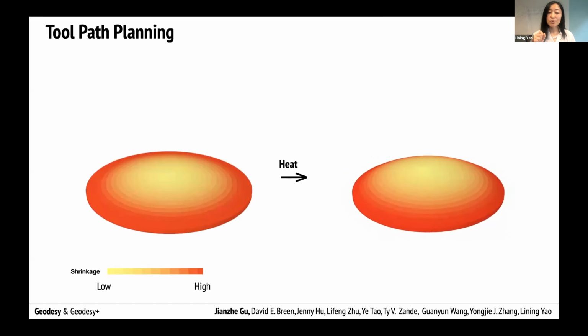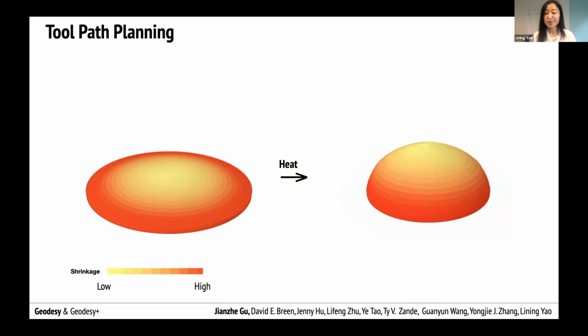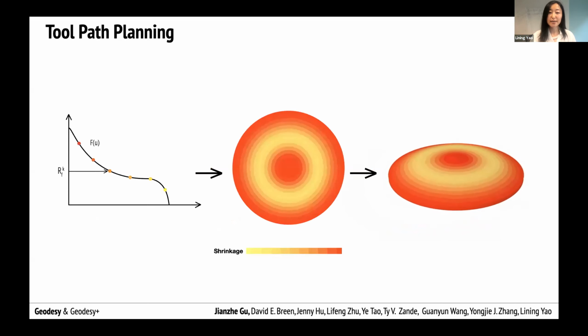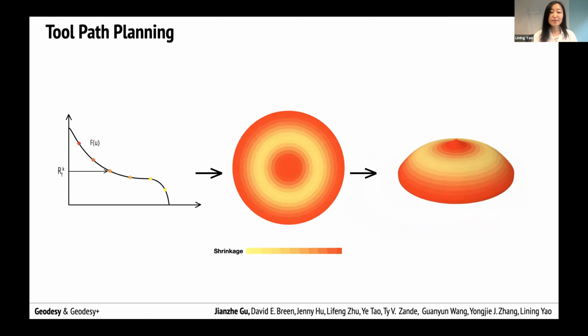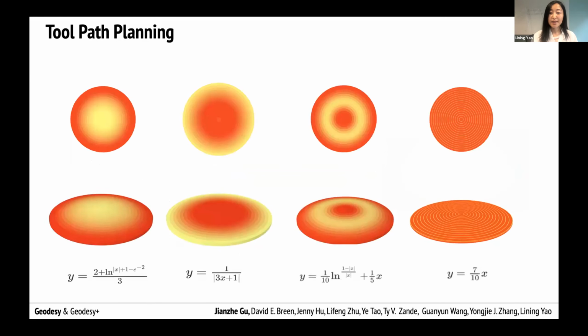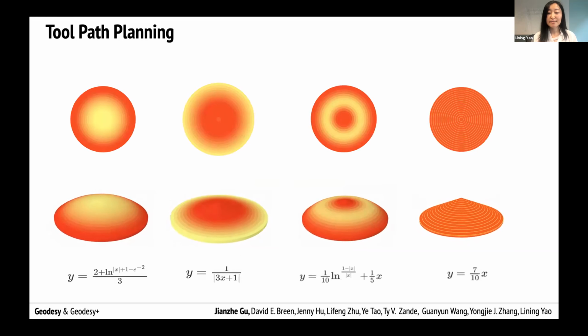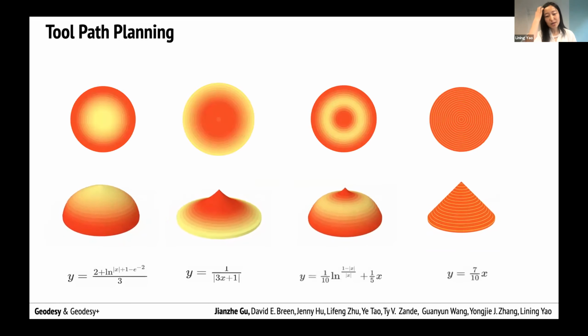And if you start to tune the local shrinkage ratio, assuming you can do that. At this point, we didn't know how to do it yet, but assuming you can tune the local shrinkage ratio, then you can really play with the profile of this center symmetrical shape. And by simply calculating the geodesic distance and also how far each point is from the center axis, right? With this method, you can pretty much print shapes or morph shapes that can be mathematically defined. Again, at this point, they are all center symmetrical.